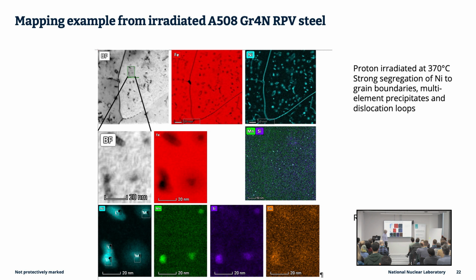Which brings me to one of my areas of doubt on radiation-induced segregation. There's quite a lot of effort expended on mapping grain orientations and trying to correlate different grain boundary characters with different quantities of segregation. It's just not that simple, because all you've got to do is look at any grain boundary in an image like that, and you realise that it's different along its entire length. There's no such thing as a particular orientation for that grain boundary. It's just different everywhere. And I think the best you can ever do really is to analyse a number of grain boundaries, if that's your thing, and try and see what the spread of segregation values is.